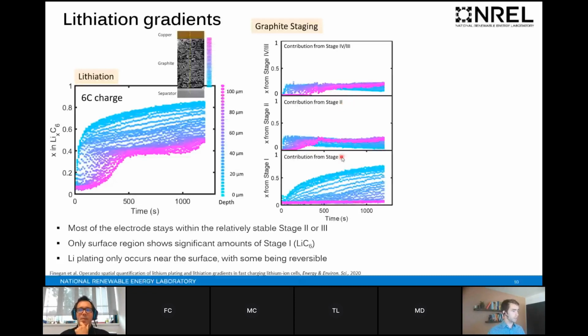And this has consequences that I won't go into in great detail in this talk, but they're covered in this paper on the behavior of graphite and the influence of Gibbs free energy barriers to phase transitions. So we can see, firstly, at the surface, very rapid growth of stage 3, also rapid growth of stage 2, and then that starts to decrease. So the surface has a high concentration of stage 3 and 2, but then it starts to decrease, and that decrease is correlated with an increase in stage 1. So it transitions to stage 1. But you can see that only really the top 40 micrometers or so actually reaches any fraction of stage 1. Most of the electrode doesn't reach it at all.